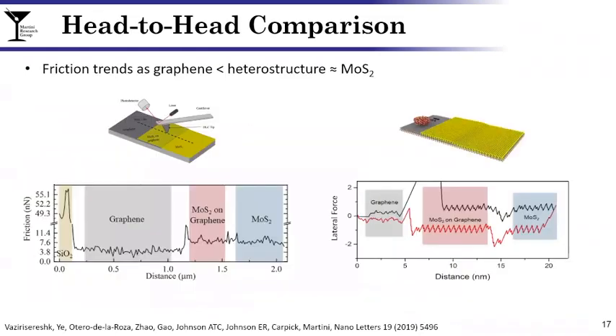Shown here are the results of one such measurement. On the left are the experiments, and on the right are the simulations. The friction corresponds to the line that you're looking at. And what you can see right away is that both in the simulations and the experiment, there's higher friction on the MoS2 than the graphene. Maybe there's a bit of difference in the heterostructure, but it's not evident in this particular analysis. But right away, we can see that there's some contrast between the MoS2 and the graphene.